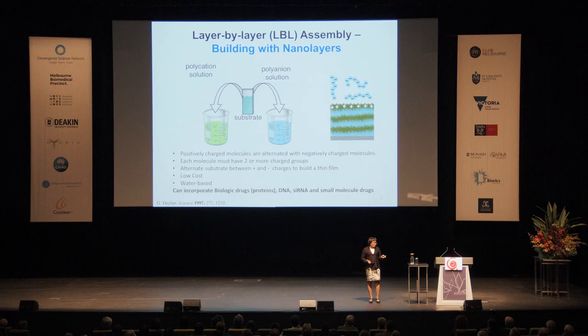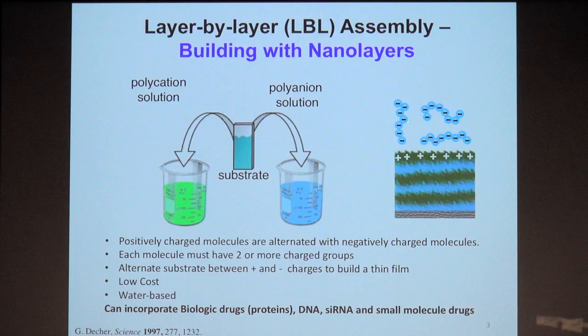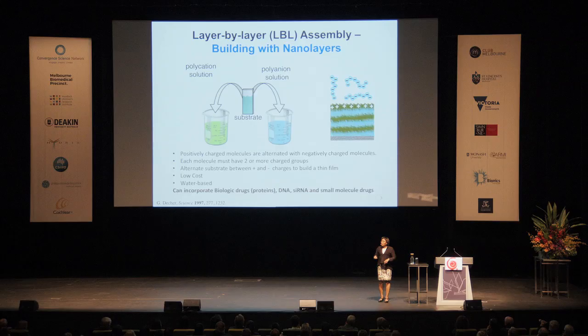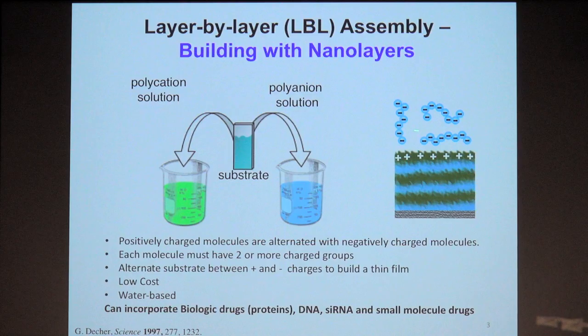But a lot of the materials that we work with are polymeric. They're long, large macromolecules that are sort of windy. You can think of them as strands or long, ropey molecules. These are actually going to interpenetrate with each other, so they're actually a bit fuzzy, these layers. They're not very clearly defined. And on the very tiny length scale, you can imagine that they're entangled. But I can build up many layers that contain, let's say, a blue and a green molecule, an alternation, and then stop and begin to add layers that have a red and an orange set of molecules. I can introduce different molecules into the system, and there's no limit to how many layers I can build as long as I reverse the charge.